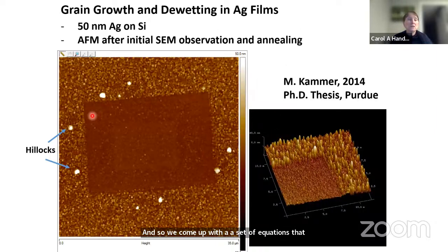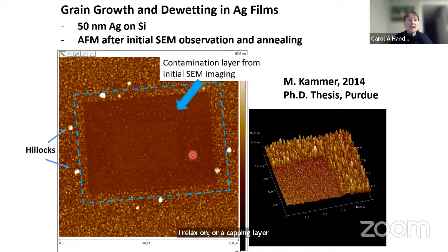And here's one set of experiments we were doing in silver. This illustrates in silver what happens if we put even an organic film on the free surface. This is a 50 nanometer thick film on silicon, and we heated it up and cooled it down. The student did extensive microstructure analysis through here in EBSD. And unfortunately, that led to formation of an organic film on the surface. What you're seeing on the free surface, these are AFM, is that the hillocks and whiskers formed outside of this region that we thoroughly characterized. So this actually is an illustration of the role of an oxide or a capping layer film. This was a contamination layer.